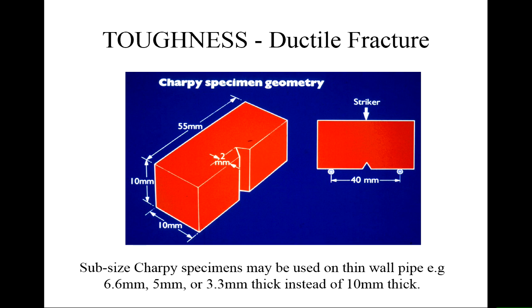So the Charpy test that is used is a standard size test piece. You can also use half size or third size test pieces depending on the wall thickness of the pipe. This has to be cut out of the wall thickness with the notch aligned in the longitudinal direction so that you can get the effect of the hoop stresses. So it's a 10 millimeter square bar, 55 millimeters long, with a 2 millimeter deep V notch cut into it. You can buy from most suppliers special cutters designed to produce the geometry of the notch that you need.